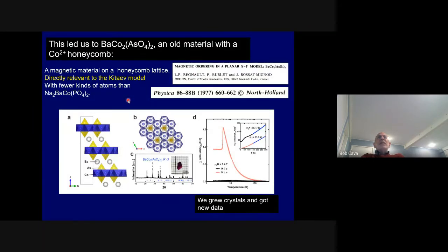Now this material came about in the 1970s, and it was studied in the past. It has a honeycomb lattice of cobalt, and under zero field, it magnetically orders. So here is the temperature-dependent magnetic susceptibility of barium cobalt arsenate. It can be grown as single crystals. So here's a single crystal of barium cobalt arsenate. It has a layered honeycomb lattice of cobalt atoms. And you could ignore this and say, okay, it's not interesting. Or you can learn from ruthenium trichloride and put a magnetic field on it and see what happens.